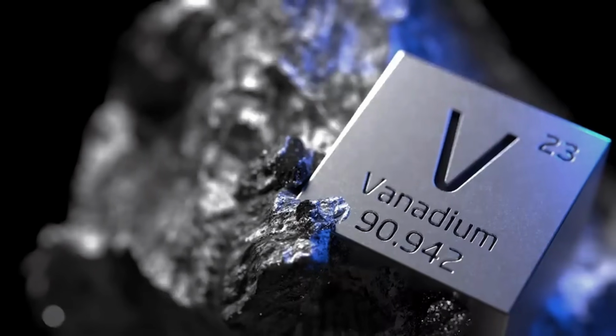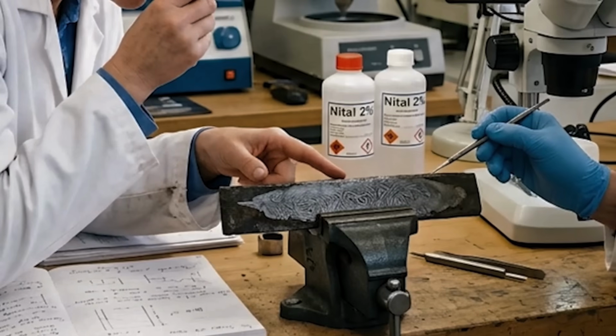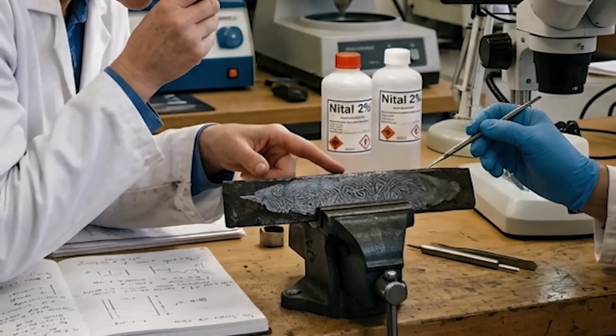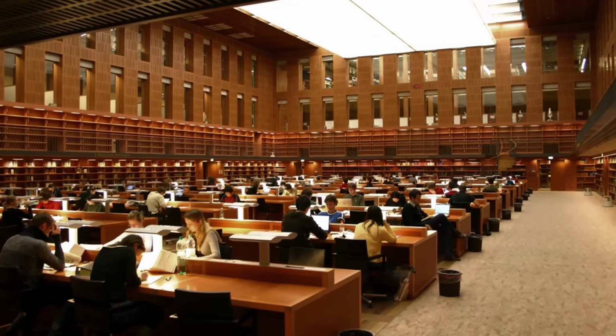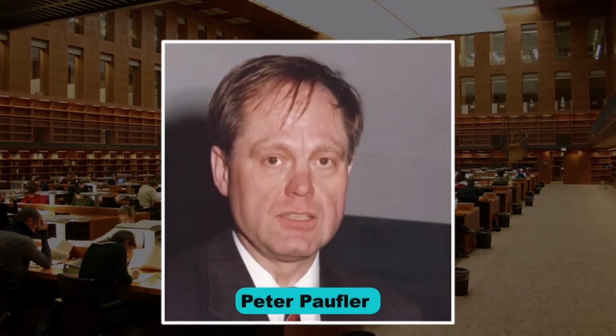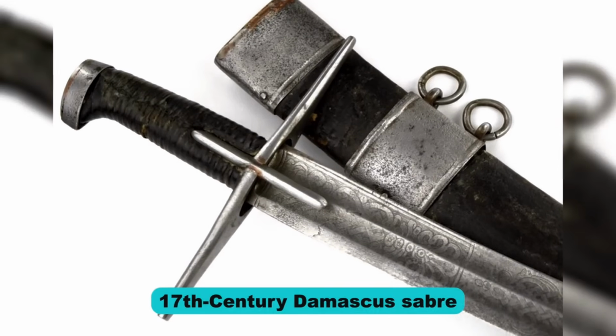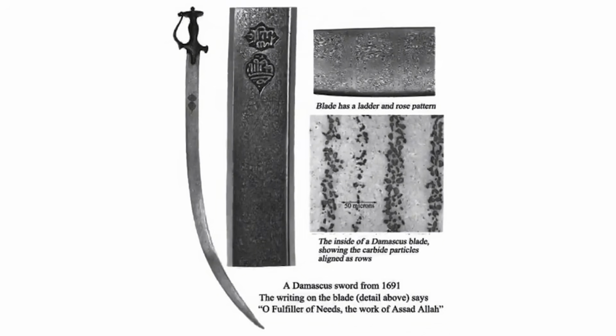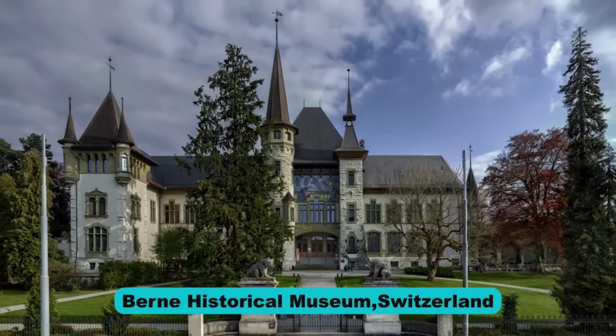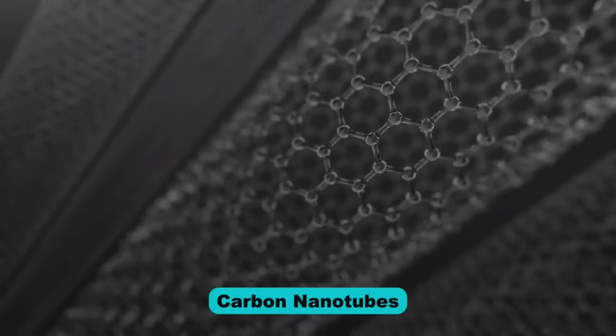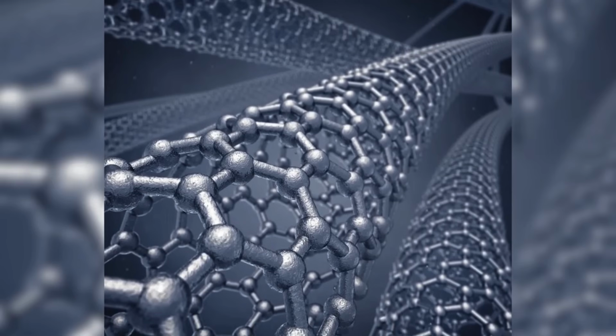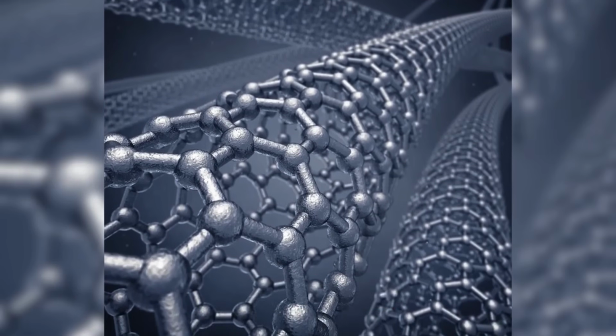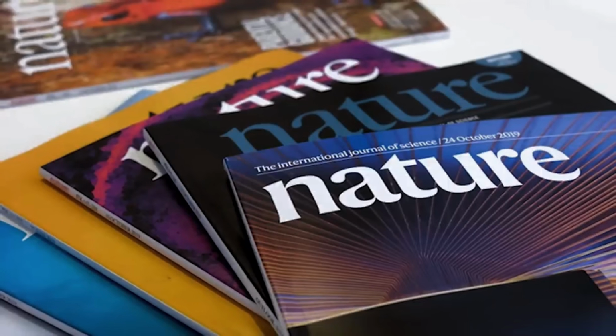But the vanadium was only half the story. Because when another team of scientists looked even closer, what they found inside Wootz steel should not have been possible. In 2006, a research team led by Marianne Reibold and Peter Paufler at the Technische Universität Dresden in Germany got their hands on a section of a 17th century Damascus sabre. The blade had been made by the famous smith Assad Ullah, and it was donated by the Bern Historical Museum in Switzerland. They dissolved a piece of the blade and examined it under a transmission electron microscope. Inside the steel, they found carbon nanotubes, cylinders of single-atom thick carbon with a diameter of roughly half a nanometer, enclosing nanowires of cementite. Their findings were published in Nature.